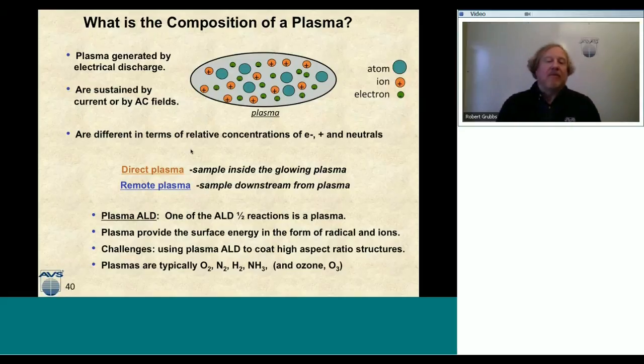The typical problem with plasmas is that there's a certain finite lifetime to them, and when I'm trying to get a plasma to go down a trench to do plasma ALD, I'm now in the molecular flow regime in a trench, and so we might just neutralize those ions and those radicals that are used to perform chemistry. So plasma chemistry doesn't work very well down trenches, depending on the aspect ratio and the overall diameter of the trench with respect to the mean free path of the plasma itself. So there's a problem with plasmas.